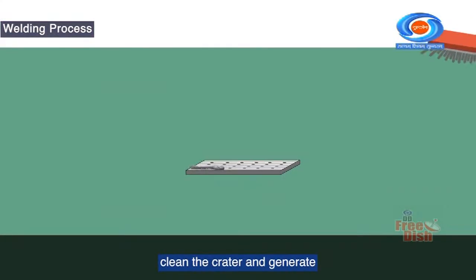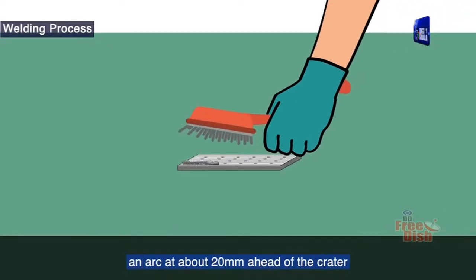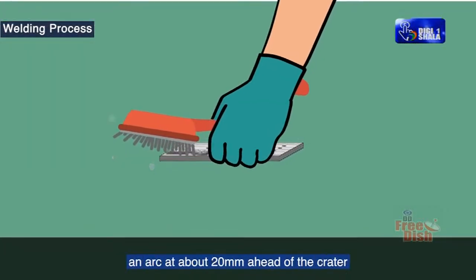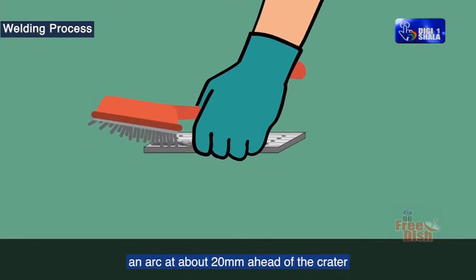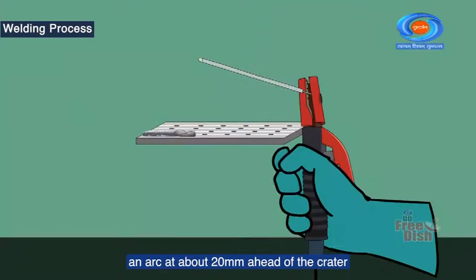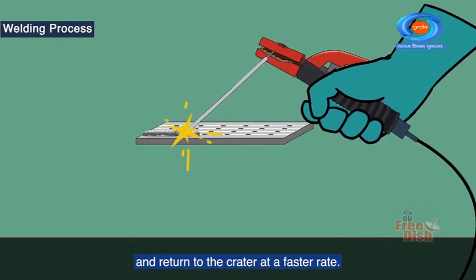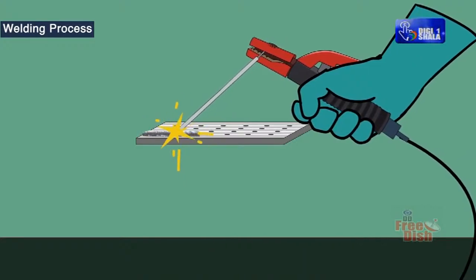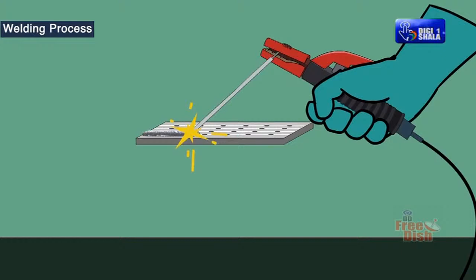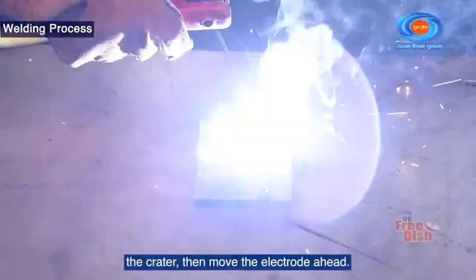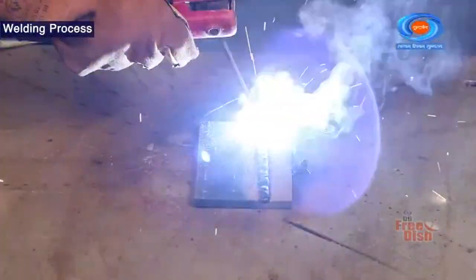Clean the crater and generate an arc at about 20 mm ahead of the crater, then return to the crater at a faster rate. Build the deposit so that it fills the crater, then move the electrode ahead.